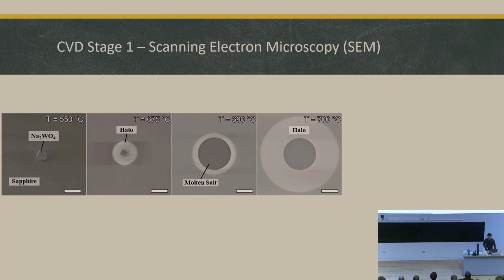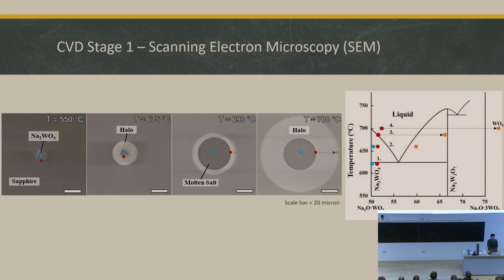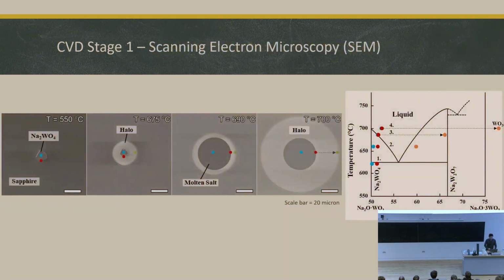So we capture different stages of these materials, and we find out that the sodium tungstate can melt and form different ratios of combination of sodium oxide and tungsten oxide. And with different temperature, the ratio between them changes. And here, marked at different positions, there are different amounts of each of these compounds.